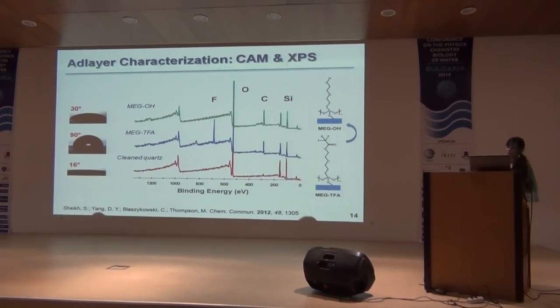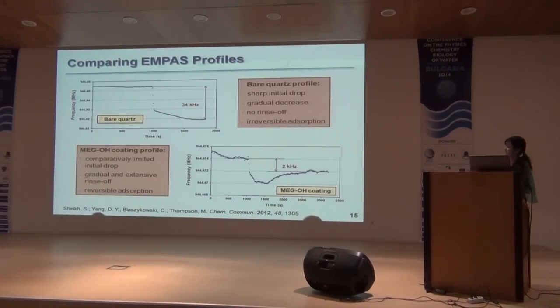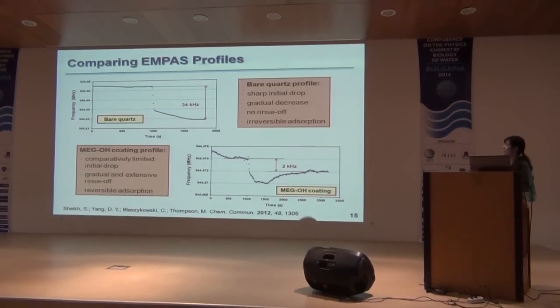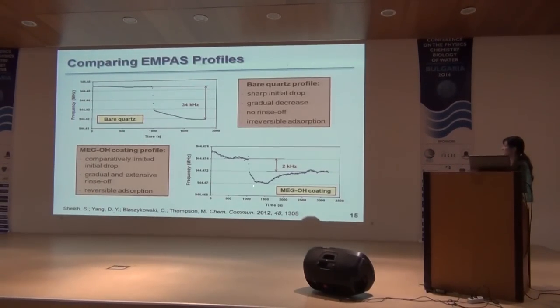With respect to the EMPAS profiles, it's not just the magnitude of the frequency shift that matters — the shape is also important. For bare quartz, we see a sharp initial drop after serum injection, a gradual decrease, and no rinse-off, which is indicative of irreversible adsorption. With the MegOH coating, we see something quite different: a comparatively limited initial drop after serum injection, a gradual and extensive rinse-off, which is indicative of reversible adsorption.